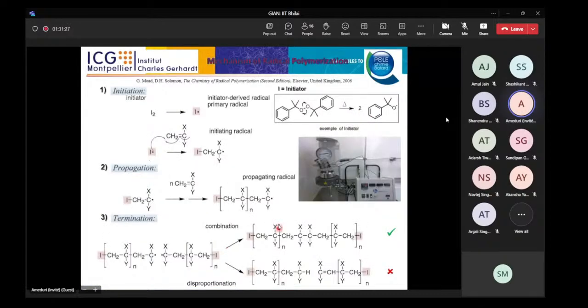The polymerization of a monomer by radical polymerization is the result of three main steps: initiation, propagation, and termination. In the propagation, of course, there is regioselectivity, but in radical polymerization, it's not really regioselective. This means that you can have some head-to-head additions, and usually the recombination of two macroradicals occurs for the termination step, while the disproportionation does not occur. And of course, all the reactions are conducted in autoclave.